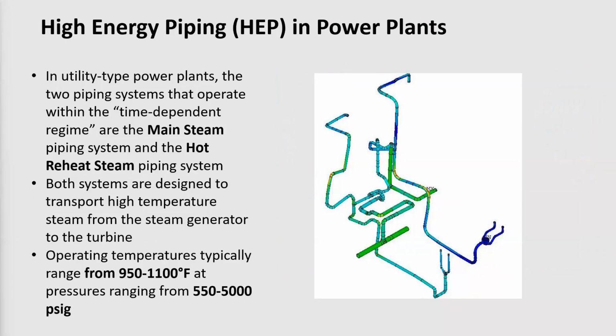So in the high energy piping in power plants, and for the combined cycle plants as well, you're generally talking about the main steam and the hot reheat steam piping systems. The intent, of course, is to transport steam from the steam generator to the steam turbine, and they typically operate in temperatures somewhere in the range of 950 to 1100 degrees Fahrenheit, and from 550 to 5000 psi pressure.